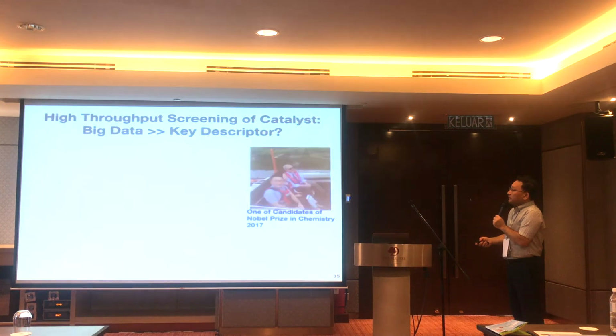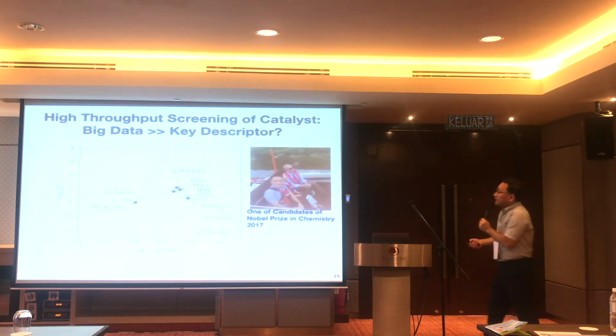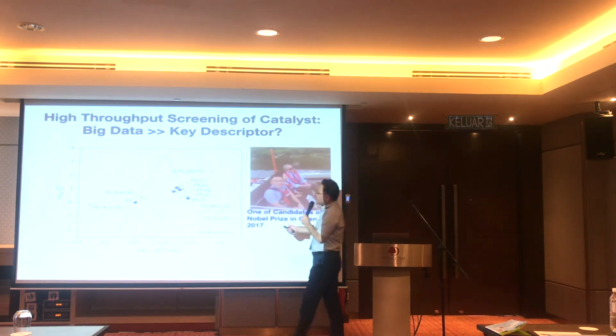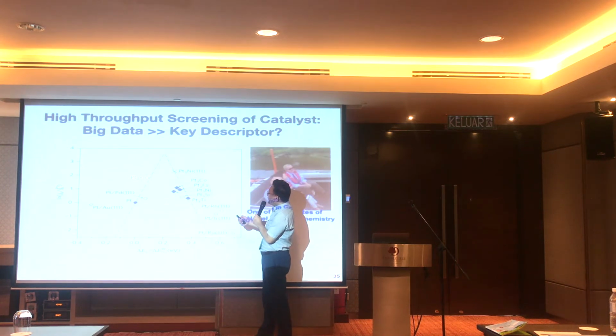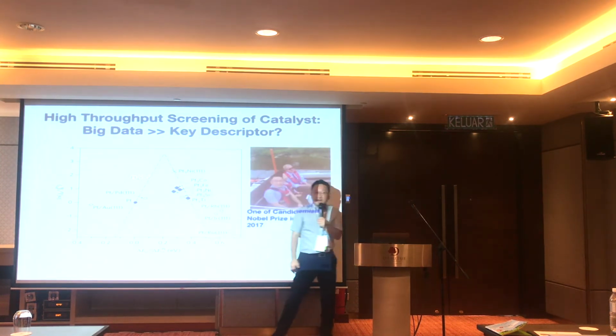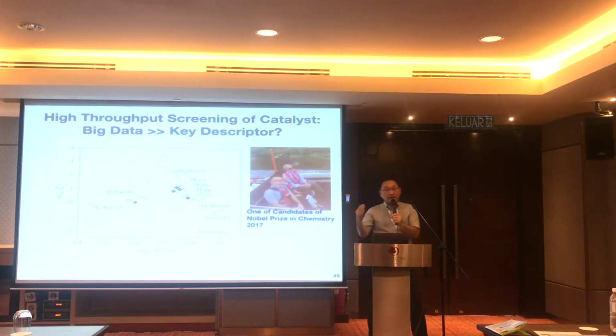You see here, these materials all utilize 3D transition metals: nickel, cobalt, iron, and cobalt, nickel, cobalt, iron, and nickel again. These materials very easily oxidize whenever there is oxygen. So Norskov proposed that you have to put this cobalt, iron, nickel in the core and coat the particle with a thin layer of platinum. Then you're going to have the best activity.